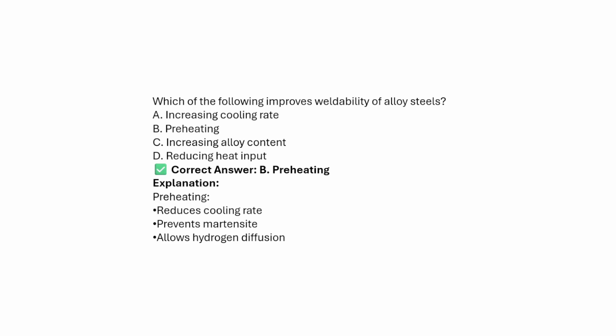Which of the following improves the weldability of the alloy steels? Option A, increasing the cooling rate. Option B, preheating. Option C, increasing the alloy content. Option D, reducing the heat input. So the answer will be preheating. Preheating improves the weldability by reducing the cooling rate. If the cooling rate reduces, the formation of the martensitic phase reduces, so it is good weldability. So preheating reduces the cooling rate, prevents the martensitic formation, and allows the hydrogen to diffuse out.